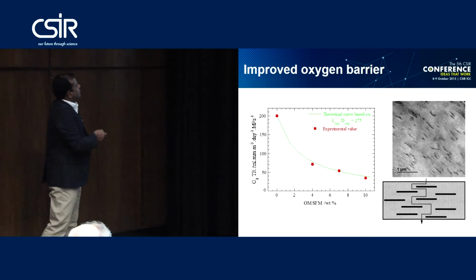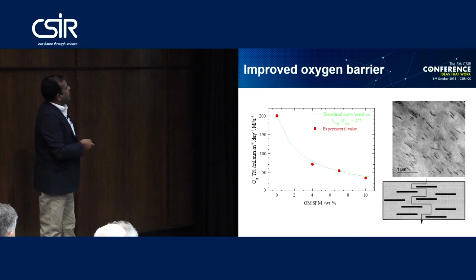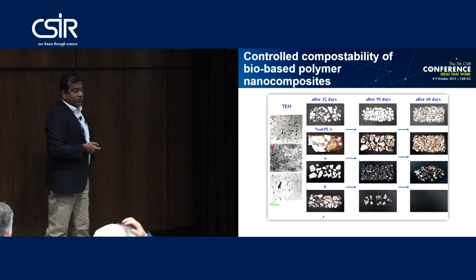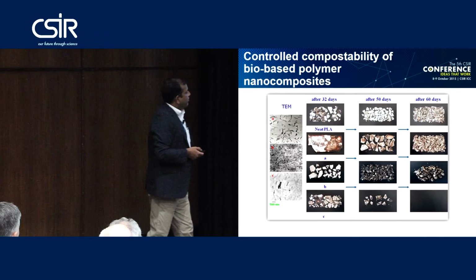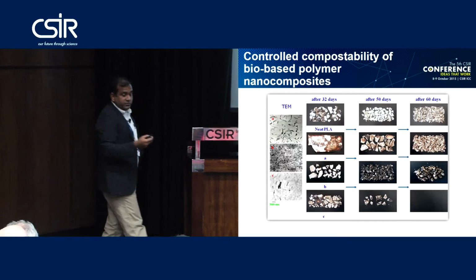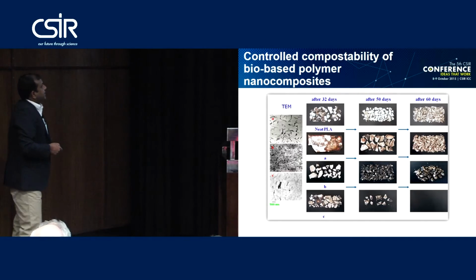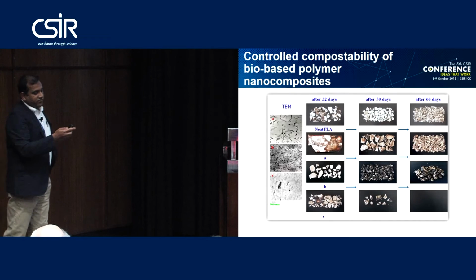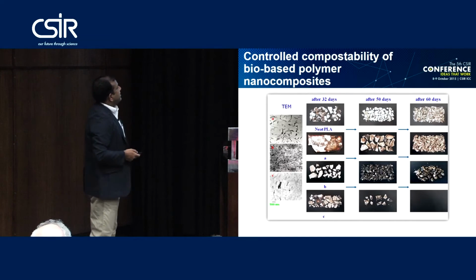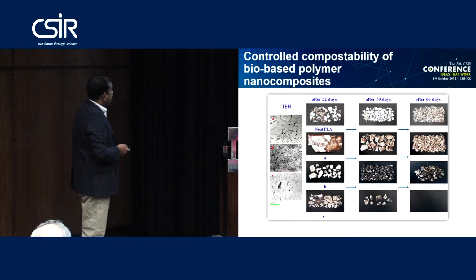So we are actually able to decrease the permeability in normal packaging, and these are PLA-based products. Finally, you can also control the degradation with nanocomposite technology. That is a huge implication for environmentally friendly products, and depending on the degree of dispersion, you can control the degradability.